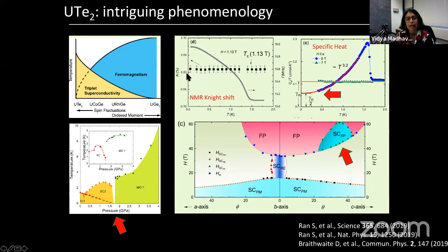So for example, I think one of the smoking gun experiments is the Knight shift, which is flat across Tc. I should mention the specific heat also, because the specific heat shows something very interesting. At zero temperature, it shows a very large residue that indicates that only half the electrons are paired in the system. So this is a big mystery, actually, even today.